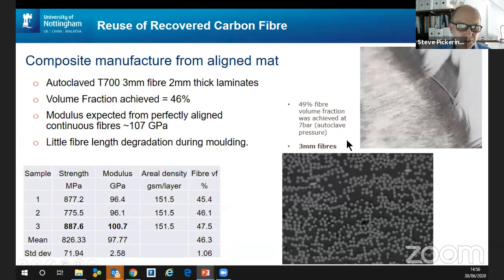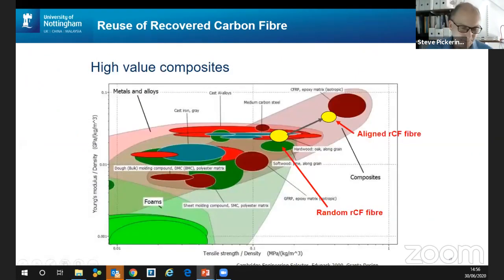So this is an opportunity. To get the highest mechanical properties, you need to have processes to align the fibers. And we were getting up here towards the composites we'd made from virgin fiber, and they were well away from the competing materials. So you're getting some of the best out of the recovered fibers by aligning them at high fiber volume fraction.